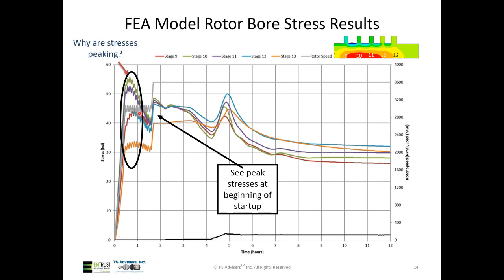And then you notice they're coming down, even holding at relatively constant speed. The answer to this is that we have two things happening at once. One is we're increasing to a significant speed, 3,000 RPM. So we have quite a bit of rotational stresses, but we also have our peak thermal stresses because we've got that really high thermal mismatch at that point in time. Because again, you may have 400 or 500 degrees hotter steam than you have metal at that point.